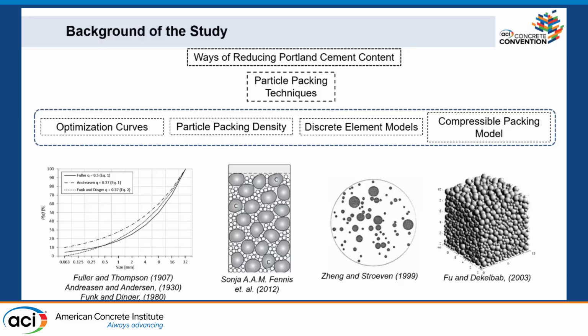We can also calculate how much of each material to use by weight to achieve our desired density. With the discrete element model, we model virtual particles of different sizes and shapes, seeing how they pack together. This helps refine our mixes beyond basic optimization curves. And the compressible packing model is an advanced model that takes into account how particles deform slightly under pressure. It gives us even more precise predictions of real-world packing behavior.